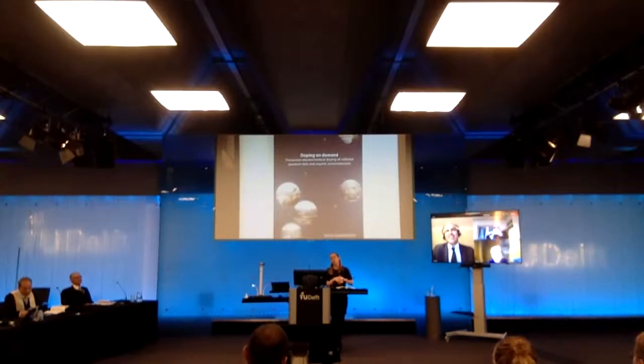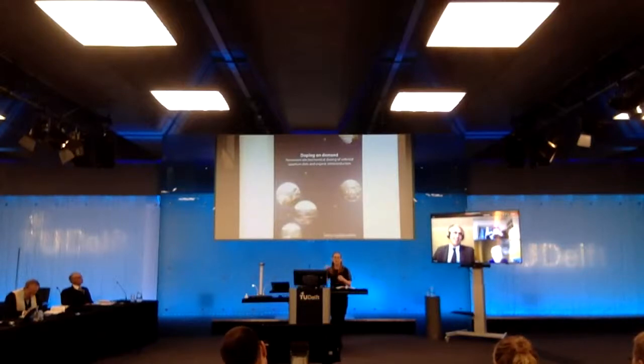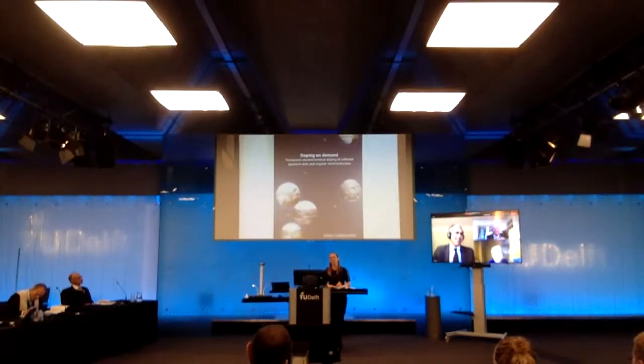It happened very quickly, at very low concentrations of oxygen, that the electrochemistry started to become worse. We did not measure the absorbance, but after prolonged exposure to oxygen, they actually fell off the ITO. So I really know that oxygen is able to degrade my quantum dots. And like I said, in the end, there were some quantum dots floating on top of the solution. So oxygen, yeah, it really does.